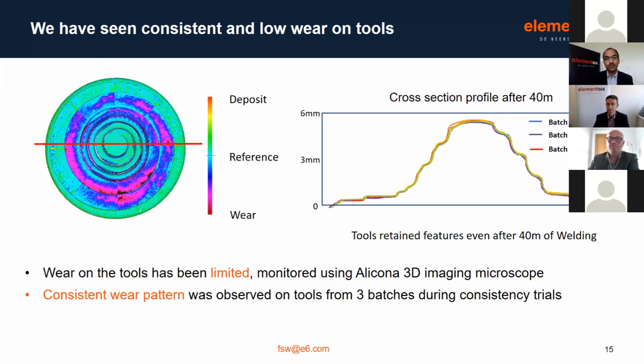We used a 3D microscope, Alicona, to generate these wear profiles, which demonstrated how the tool wears. So, for example, on the left image, the pink and the red areas are where you see the tool starts wearing. On the right, we made a cross section of those profiles, and you can see after 40 meters of welding, how nicely they overlap with each other, which demonstrated the wear on the tool has been consistent, and it was reflected on the weld as well.